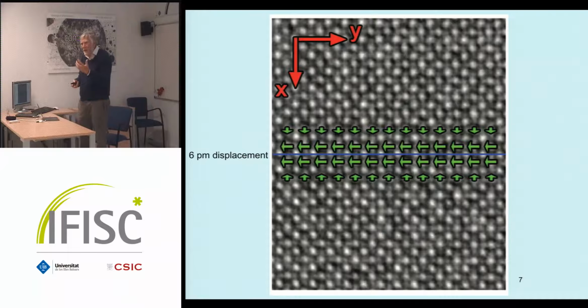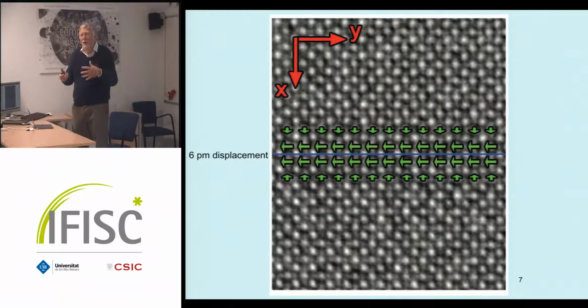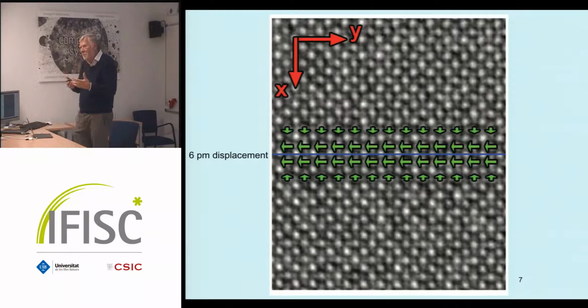But you have to be very careful that it's only the nano-structure inside the big structure which is the carrier of the information. It's not the structure as such. And so when people in the past measured this stuff and said, is there piezoelectricity? Of course there's piezoelectricity. You can see it here. But they couldn't measure it because there are very few domain boundaries, and therefore you have such a weak signal, it's within the noise. So you have to think how to measure it properly and what methods you have to use.